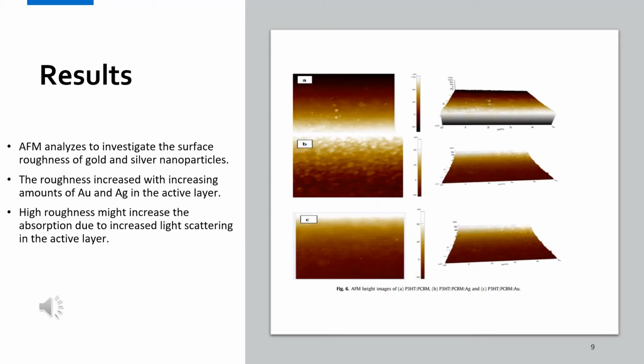This result is obtained by making the atomic force microscopy analysis to investigate the surface roughness of gold and silver nanoparticles. Figure A shows that surface roughness was not observed where no particles are added, while Figure B indicates that Ag nanoparticles on the surface caused surface roughness and have many agglomerates. Figure C shows that Au on the surface caused very little roughness and agglomerates. The roughness increased with increasing amount of Au and Ag in the active layer. Also, high roughness may contribute to an increase in absorption due to increased light scattering in the active layer.